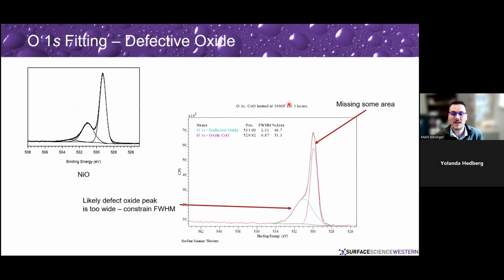If we look at standard curve fitting of an oxygen peak, like if we look at something like nickel oxide, you get this main peak, this main lattice peak. That's what you would call your typical oxide. A lot of times you're going to see these higher binding energy peaks as well. And so some of this is going to be from adventitious carbon, and you can calculate that. A lot of the time this peak still has structure. It can be a little bit of surface hydroxides. It can also be defective oxide. So within your lattice structure you have oxygen that's got vacancies of nickel or missing things or just defective edge locations and weird sorts of defects that can cause that oxygen peak to have a higher binding energy. It's still part of that lattice oxide, but we call this defective oxide.